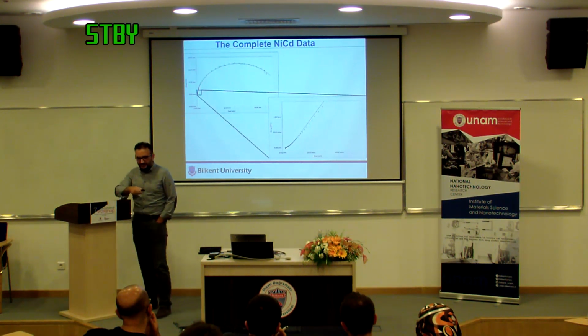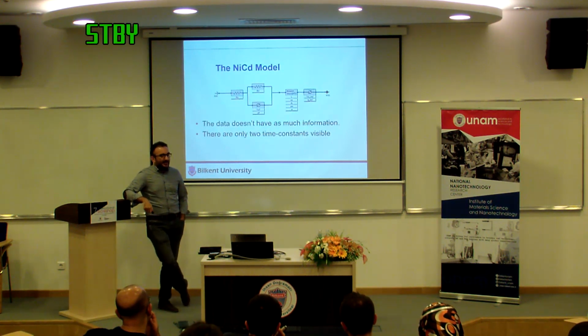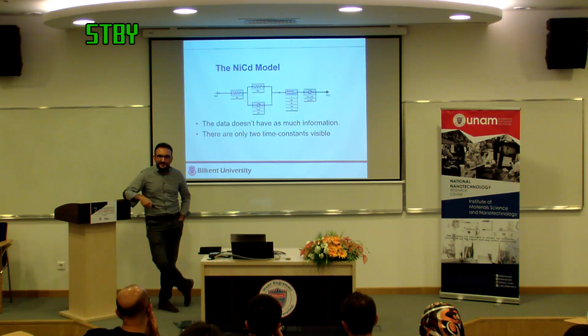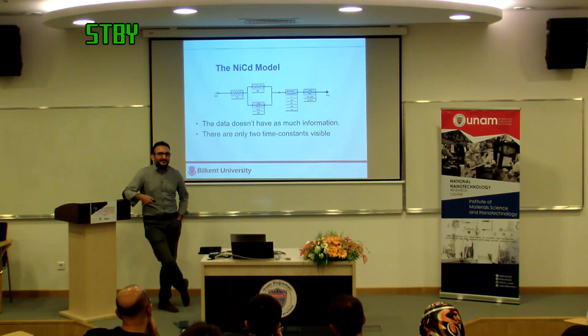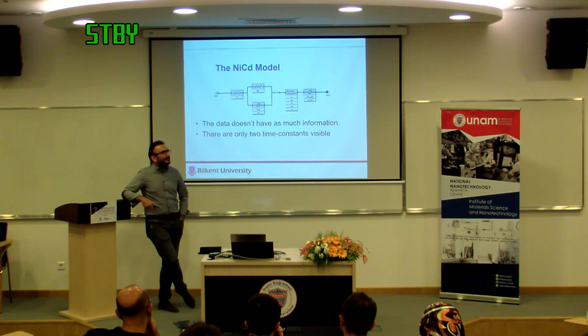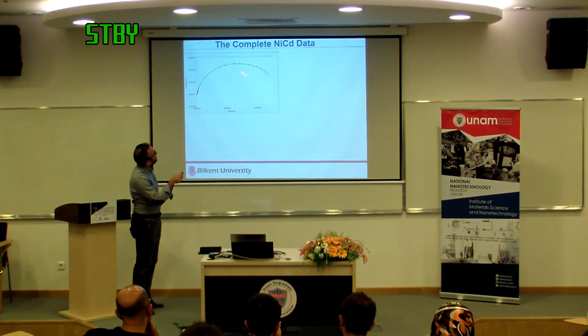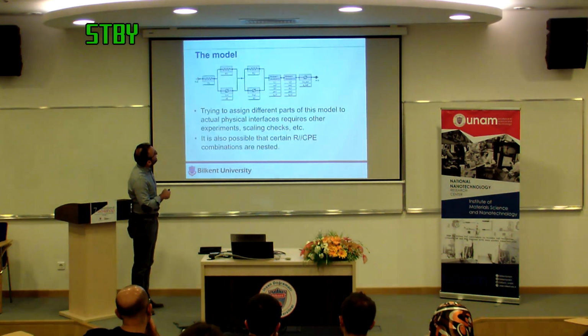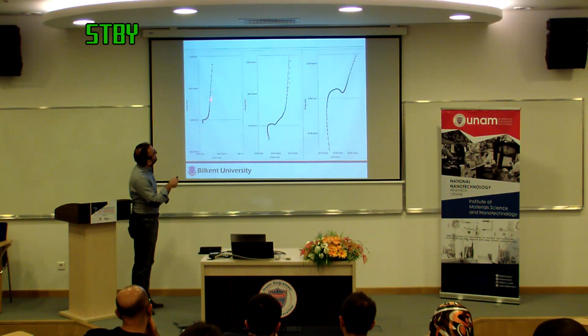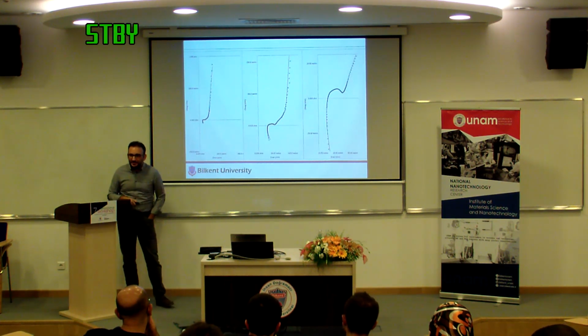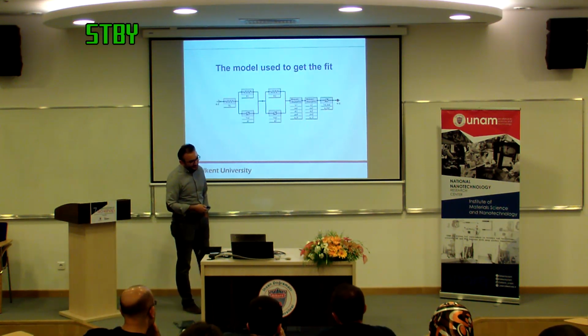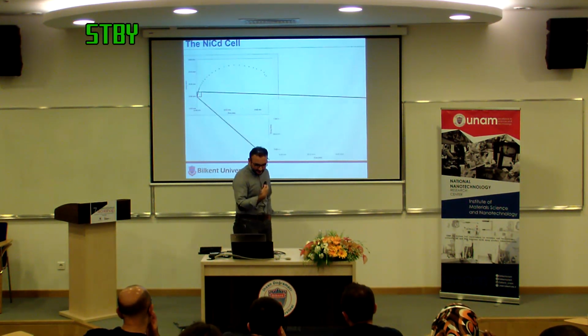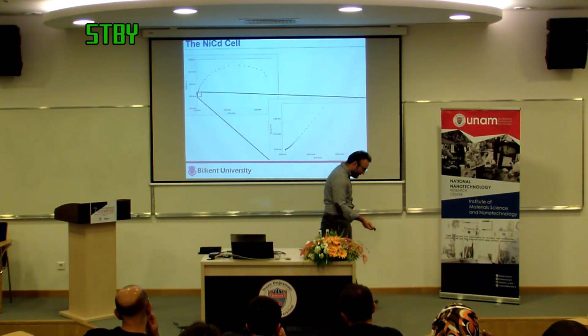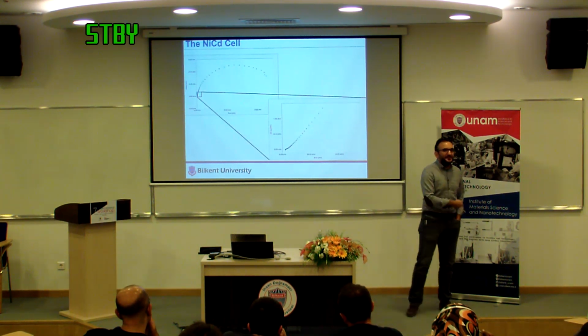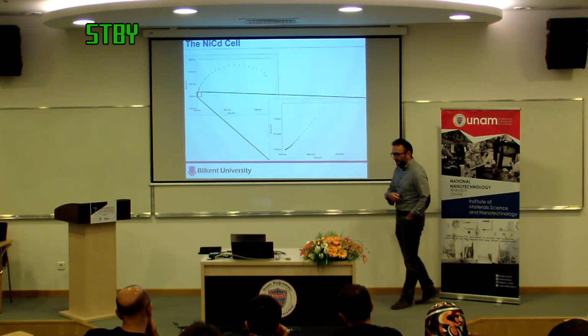And I could extract information out of here that I could not extract in the lithium-ion data. The biggest difference here is the fact that this nickel-cadmium actually has a horrible self-discharge, and the lithium-ion did not. So the fact that this semicircle closes, whereas this large one didn't, has to do with the self-discharge. And because the nickel-cadmium had a horrible self-discharge, I could resolve a different feature, but that ended up hiding a lot of the other features that I could resolve in the lithium-ion.